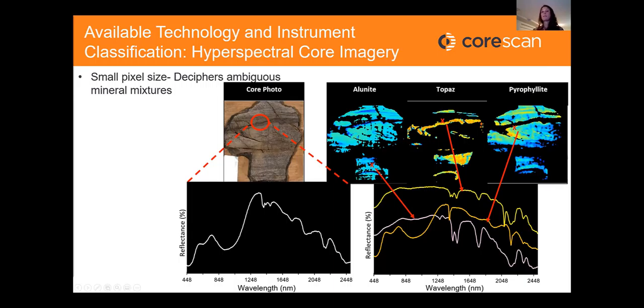So there are numerous advantages to hyperspectral core imagery. The small pixel size is able to help a spectroscopist pick apart what would normally be an ambiguous mineral mixture or spectrum. Over here on the left is an example of a potentially ambiguous spectrum due to a 1 to 2 centimeter spot size. But over here on the right, you can see that as we increase our spatial resolution, we reduce our pixel size to 0.5 millimeter and can break up the spectrum into its contributing components, which in this case would be alunite, topaz, and pyrophyllite.